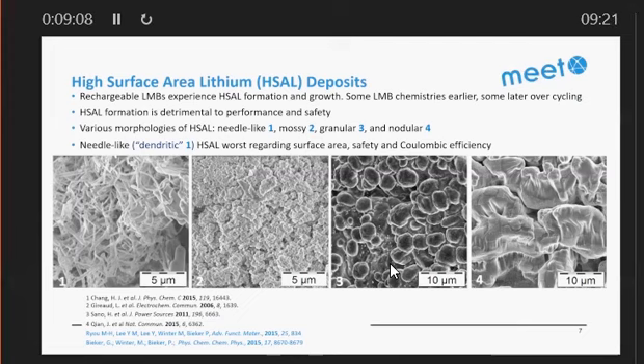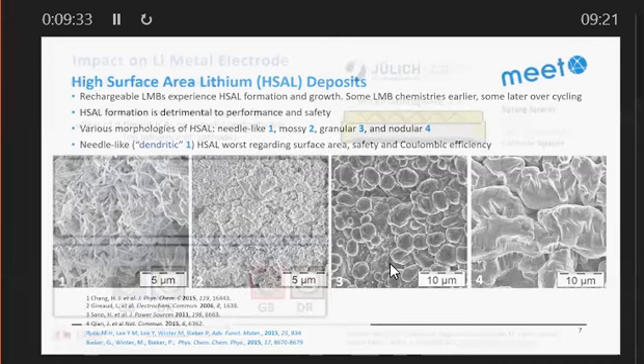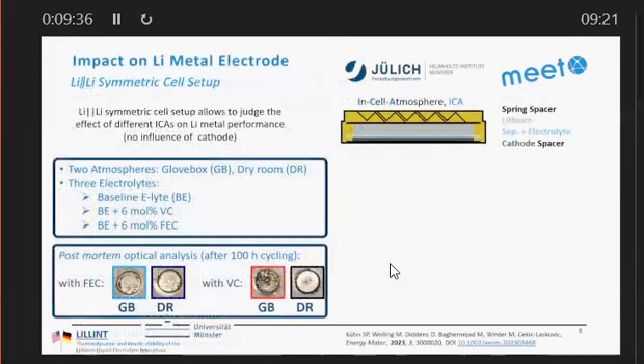I think most of the people who are a little bit longer in the field know this already. There are various morphologies. Here we have 4 that we prepared by ourselves. We have the so-called needle-like morphology, which is called dendrites. Then we have the mossy morphology, and we have a granular morphology and also nodular morphology. And especially the dendrite lithium, that's the worst with regard to surface area, because surface area means more reactivity with electrolyte, safety, and coulombic efficiency. Okay. A lot of people are trying to make lithium metal better.